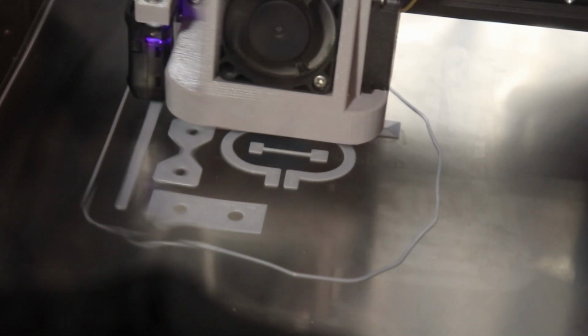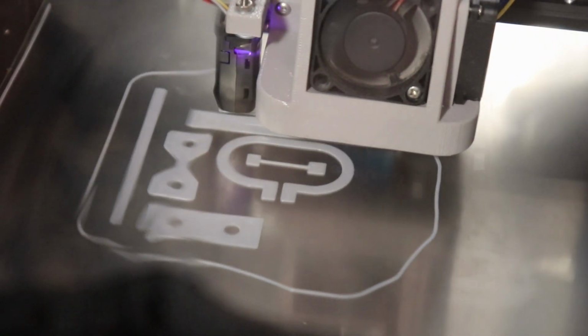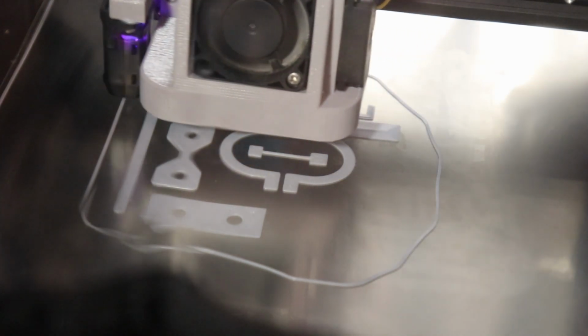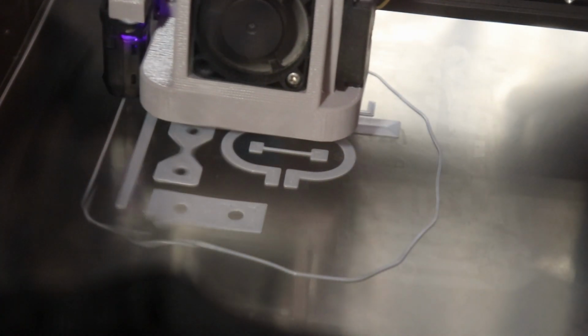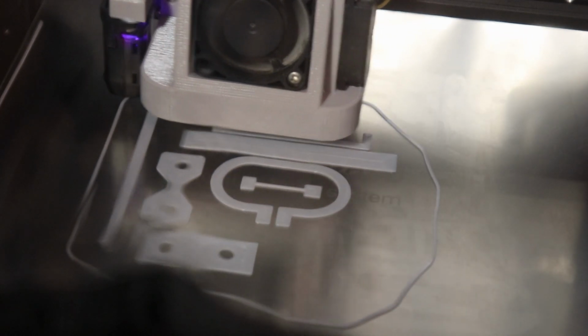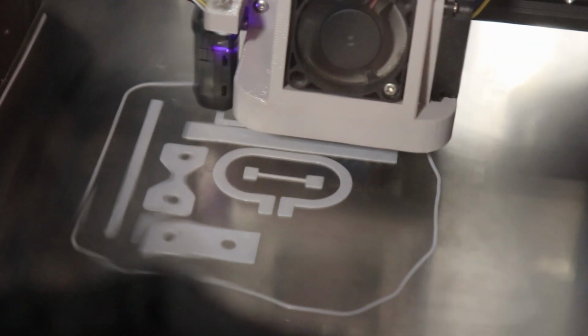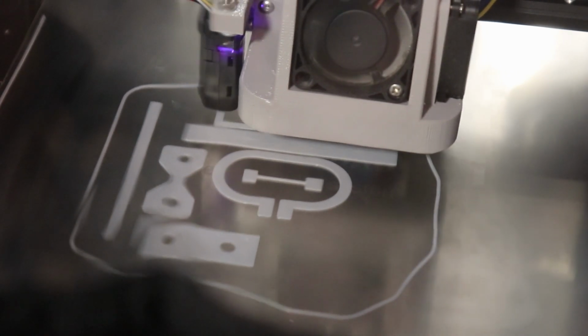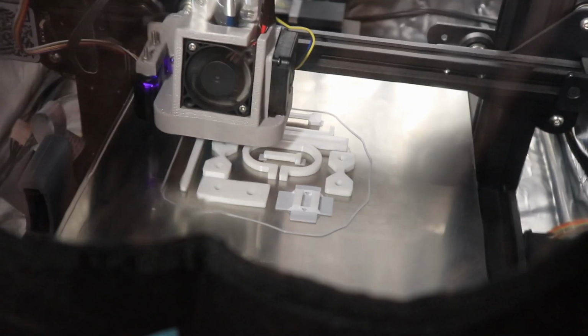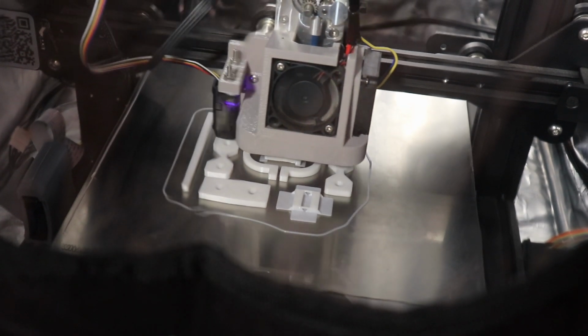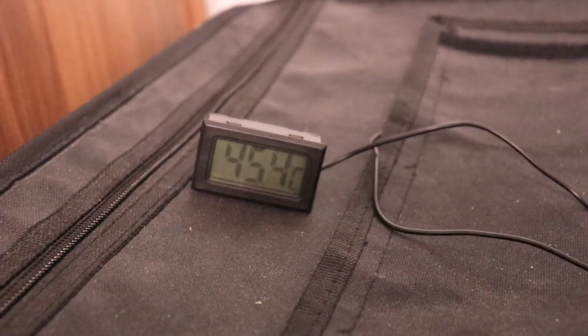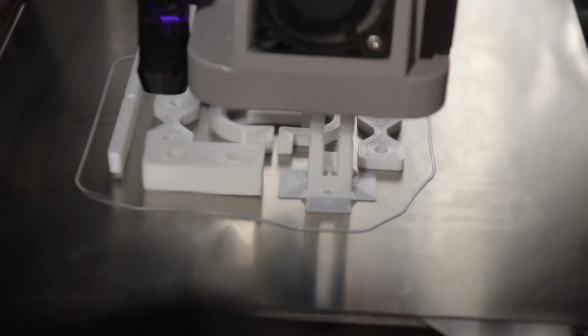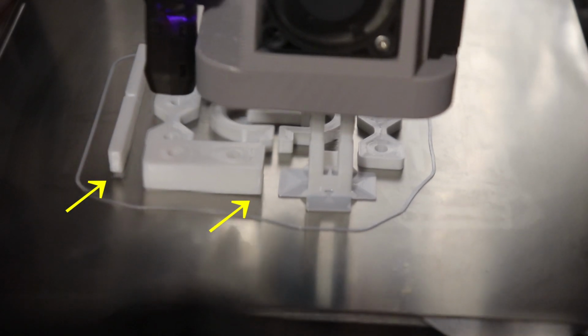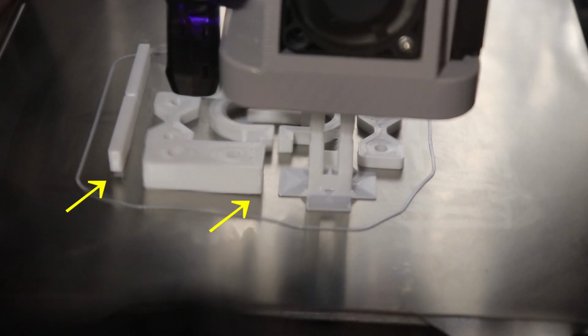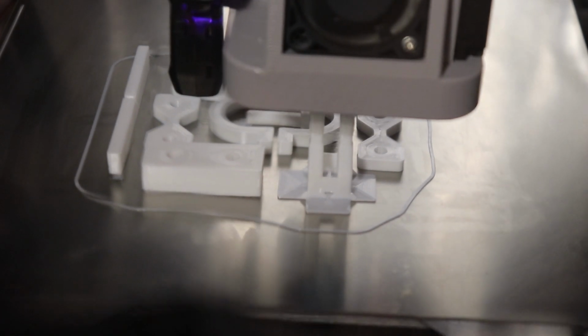So far so good. That's the perfect first layer, and I'm printing everything on 250 degrees Celsius, and I'm using only 12% cooling. Officially it's not recommended to use any cooling, but 12% is not much, but I have to use it because of those big overhangs on those vertical test specimens. Looks okay so far. I cannot see any signs of the warping, and the temperature inside the enclosure is 45 degrees Celsius. Well, actually now I can see some warping on the two objects. Maybe I should use the brim, but I forgot to enable it on this printing.